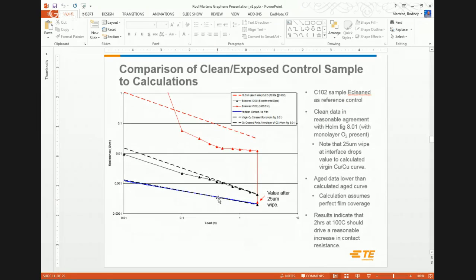So continuing that exercise, just to verify a few things, if we start down here at the bottom, our calculated curves are down here for perfectly clean copper interfaces coming together. So the blue would be my calculation. The black dashed line down here is a reference from literature. You can see they agree pretty well. However, anytime you bring a surface out into the environment, even if it's clean, you're going to have a few monolayers of oxygen on it. And that essentially will also bump the curve up a little bit higher. So the upper black dashed line is once again from the literature for monolayers of oxygen on virgin copper.